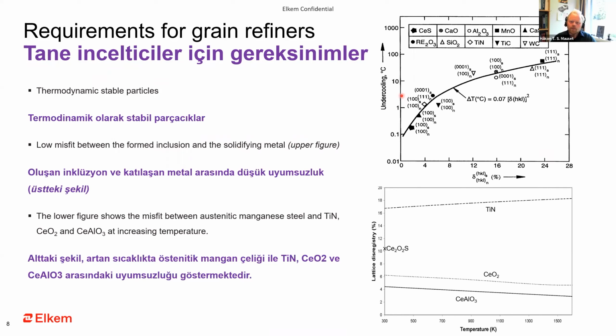In this figure here, the upper right figure, we have degree of undercooling on the y-axis, and then the degree of misfit at the x-axis. And essentially, when we speak about misfit, you have to think that these inclusions or particles that we will use for grain refining can be various oxides or sulfides or oxysulfides. And the lattice structure of the particle needs to fit well with the solidifying steel. So if we look at this figure here, we see that, for example, manganese oxide, MnO, is up here at the far right corner. So we see that it has a very high misfit between the solidifying steel lattice and the MnO matrix, and you would need a very high degree of undercooling in order for the MnO particles to be a nucleus for the steel.